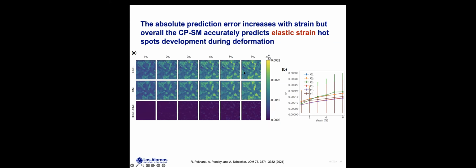So here I'm plotting the strain tensor component along the loading direction for one of the middle slices from the 3D microstructure. And you can see that the top row is from the direct numerical simulation, and the second row is the predictions from the surrogate model. And the model is able to capture these local structural details and hotspot formation that's predicted by the EVP-FFT model.